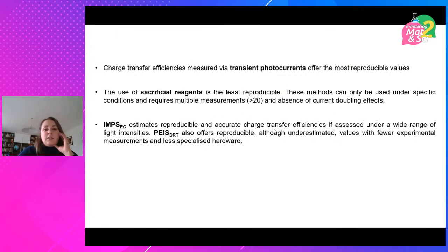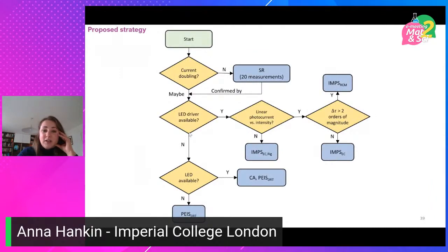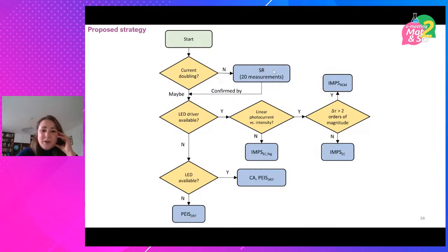So what Frankie concluded is that transient photocurrents offer the most reliable results. Sacrificial reagents actually give less reproducible results, and that whether you're using intensity modulated photocurrent spectroscopy or photoelectrochemical impedance spectroscopy, more or less the results are actually quite all right. And what he's done is he proposed a strategy, which I know there's some abbreviations here, for which I should have probably provided a code, but it will be available in the paper when it comes out, is kind of a proposed algorithm strategy about what measurement is best to use depending on what you've got available and what you're observing on your electrode during kind of these first few simple tests that you do.